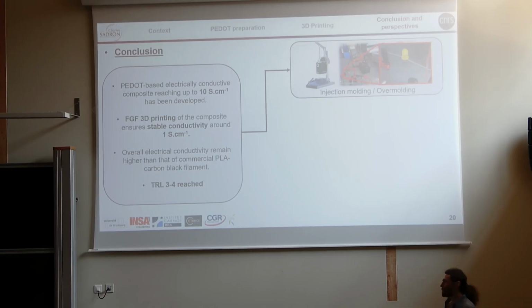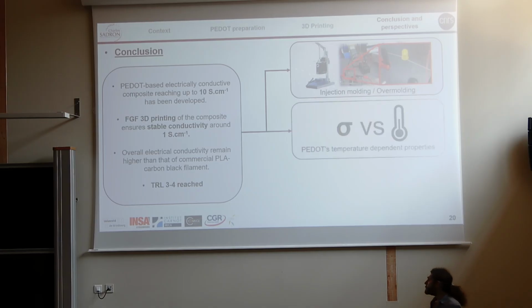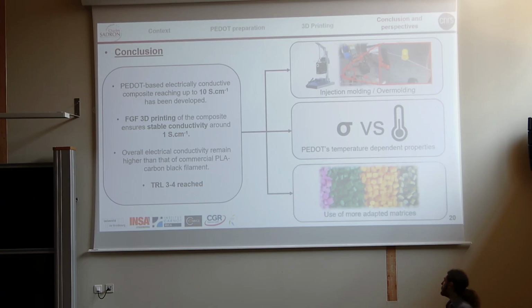For my next steps of work, I will focus on other kinds of transformation process, such as injection molding or overmolding. I was already able to make some tests on those ones, and it was quite encouraging. I will also conduct an in-depth study of the conductivity temperature dependence of the PEDOT, and the results obtained with this will help me choose a better thermoplastic matrix for the PEDOT instead of the currently used PEO, which is not very relevant regarding its melting point, for example.